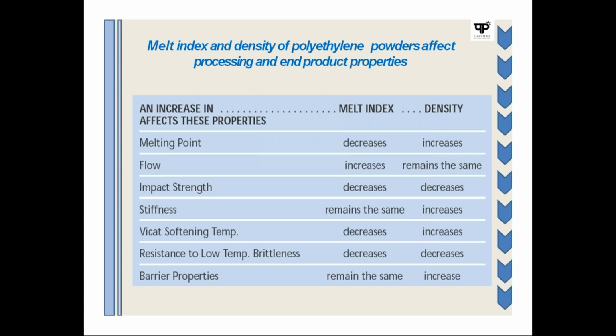Impact strength, you can see, increases when the MFI decreases and the density also decreases. Stiffness: suppose you want to increase the stiffness, then in that case the MFI, melt flow index, remains the same but density increases. Now Vicat softening temperature increases where the MFI decreases and density increases.